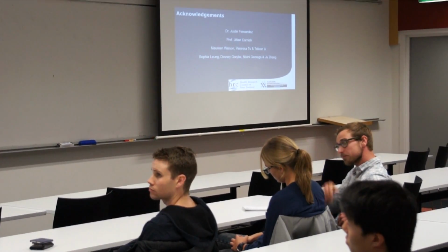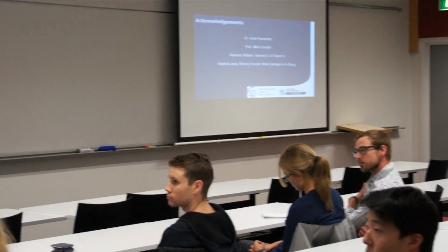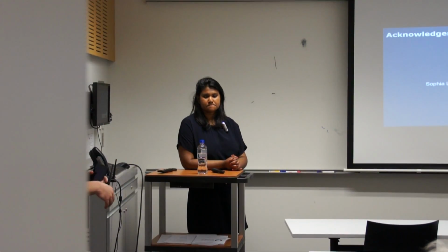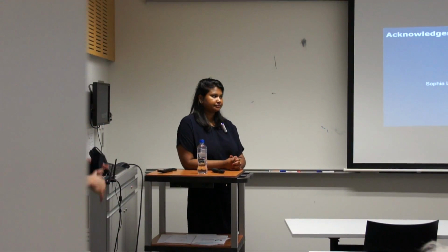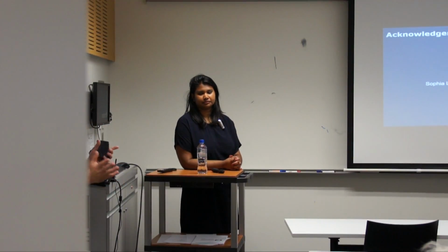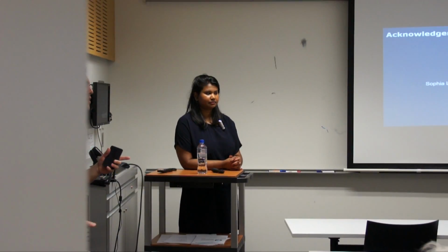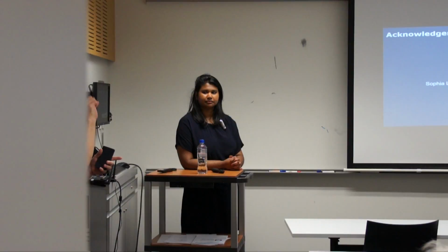Yeah, I mean, some work that is ongoing with some guys at the School of Dentistry at Melbourne University. They work a lot with the Australian synchrotron, and so they get some very nice images. And they've shown that as you age, it's the trabecular bone that goes first, and then you get an endocortical expansion. So then the cortical bone starts to thin out. So you can maintain strength to quite an age, and then all of a sudden you may happen to be walking around and it just takes a little knock to the side of your hip and you get left with this thin shell and it fractures.